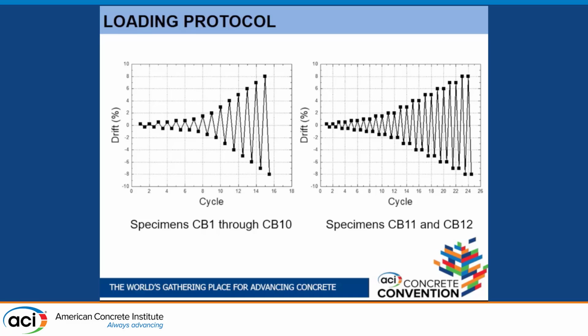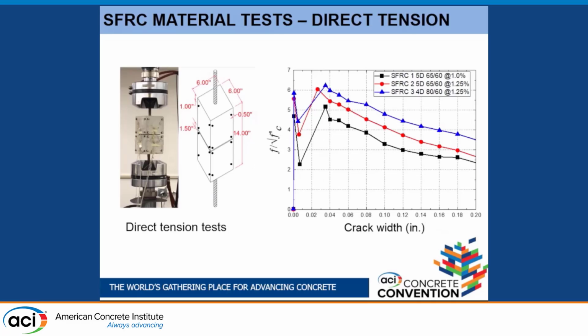We had 2 loading protocols. For most coupling beams, we had 1 cycle at each drift level. We started with basically 0.25%, and then increased to 0.5%, 1%, and so on, until failure. For the last few specimens, we did 2 cycles at each drift level to evaluate the effect of repeated cycles at each drift, and basically stiffness and strength retention during repeated cycles.